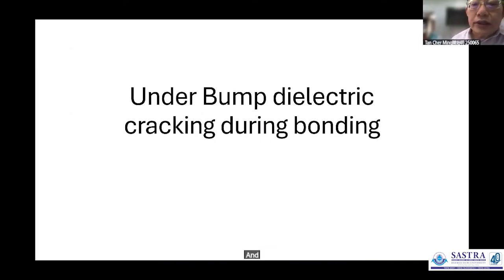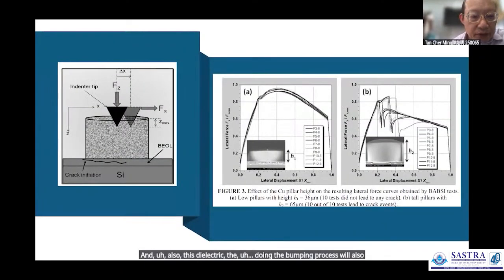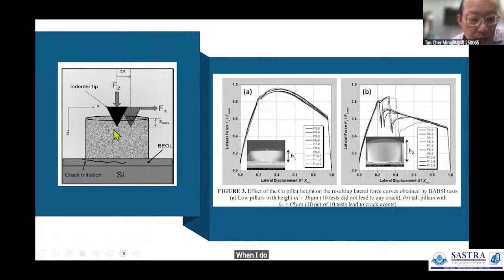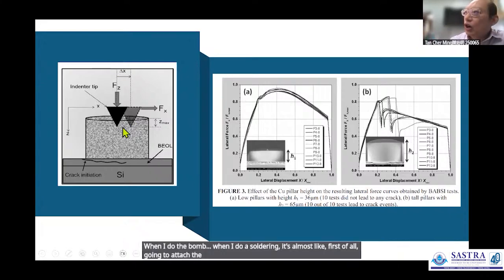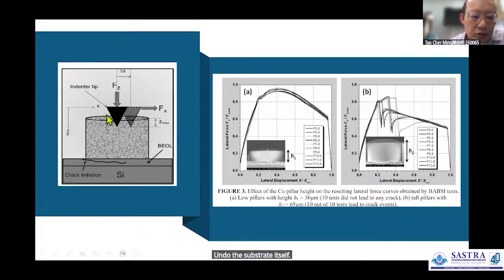And also this dielectric, during the bumping process, will also cause cracking. You can see that, for example, this is silicon. I've got a solder bump. When I do the soldering, first of all I have to attach the chip onto the substrate itself, and the solder will start to melt. So first of all, this is the vertical force. As the solder starts to melt, it actually has a pulling force. As a result, because of this force, it creates a moment on the surface of this solder bump, and this moment will cause a crack underneath because of the low-k dielectric, which has a very weak mechanical strength.